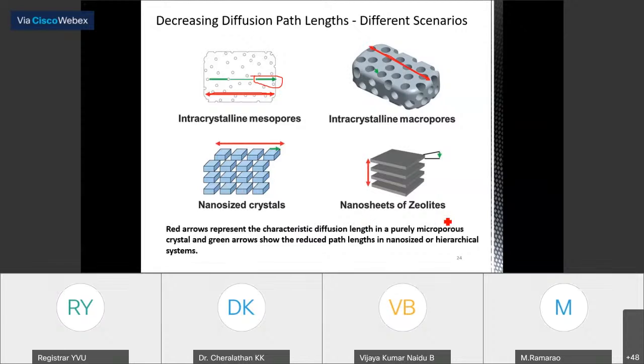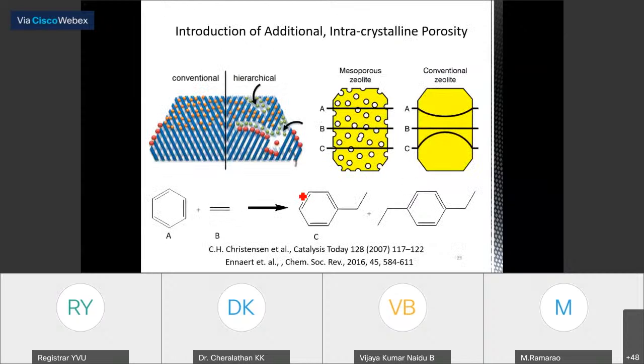The same thing happens in the case of nano-sized crystals and nanosheets of zeolites, and assemblies of these nanosheets. In all these cases, you can reduce the diffusion path length. So when you reduce the diffusion path length by modifying the size or by introducing additional porosity, you can increase the diffusivity. That is the idea. See, in many ways it will be useful. For example, if the conventional zeolite has only micropores, only the smaller molecules diffuse inside the pores and bulky molecules stay outside on the surface.